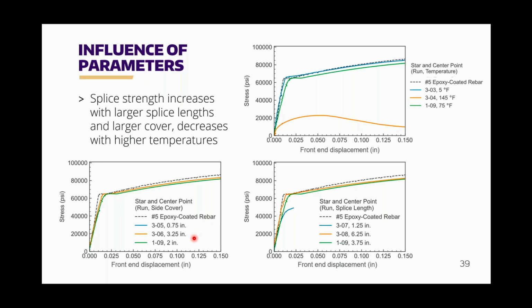It's hard to see, but for a side cover of 0.75 inches, we saw the blue curve come up and it stops about here. And so then we saw a splitting failure there. We also have temperature up here. You can see the difference between 5 degrees Fahrenheit and 145 degrees Fahrenheit. The blue curve follows the stress strain curve of the reinforcement quite closely, meaning we didn't see much slip at all in that test specimen.